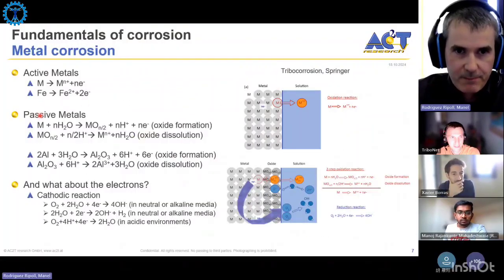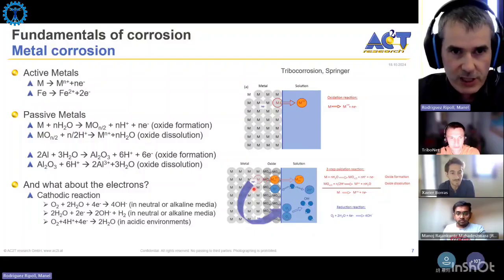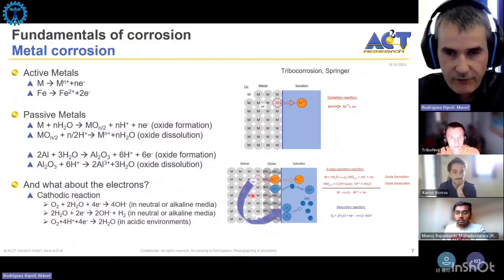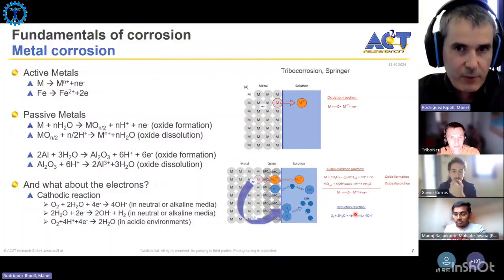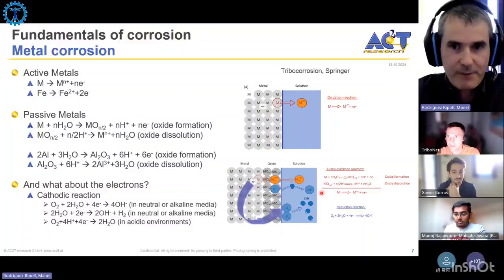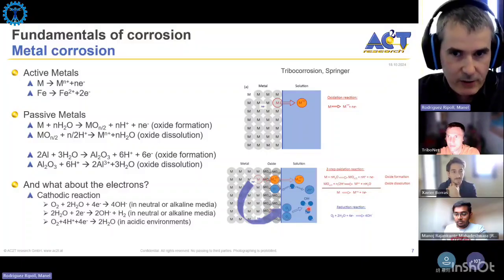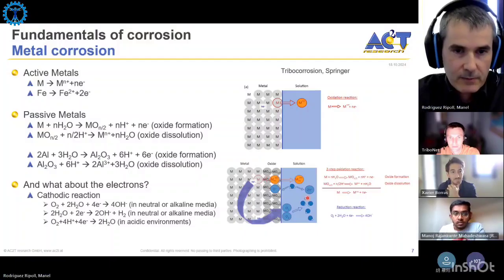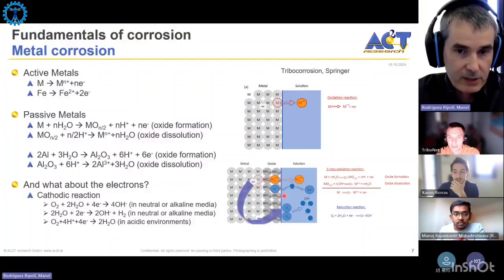So basically, when you have these passive metals, you still have dissolution, but of course the rate of this dissolution is smaller. This dissolution is done in two steps. First you have the oxide formation reaction, and then you have the oxide dissolution. So you have an equilibrium where part of these aluminum or titanium ions are dissolved in the electrolyte, but the corrosion rate is much smaller than if you put, for example, magnesium in an electrolyte, where the corrosion rate will be much larger. But even for passive metals, you still have some ions going into the electrolyte and reaching an equilibrium between the ions dissolved and the ions redeposited. So the process is the same, but the rate is the big change here. The corrosion rate is the key.